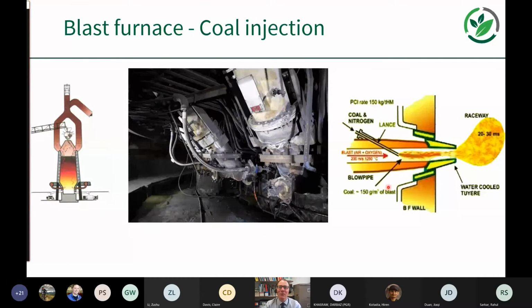So as a background into the industry and into the blast furnace itself, now I'm going to look a little bit more specifically into some of the work that I've been doing. I've been looking at injection coals. I must be quite honest that the push from the industry really is because coal injection is used to improve the efficiency of the blast furnace, so producing more for less materials. And it's been driven predominantly by this efficiency, the requirement to use different types of coals, coals that are economically more attractive.